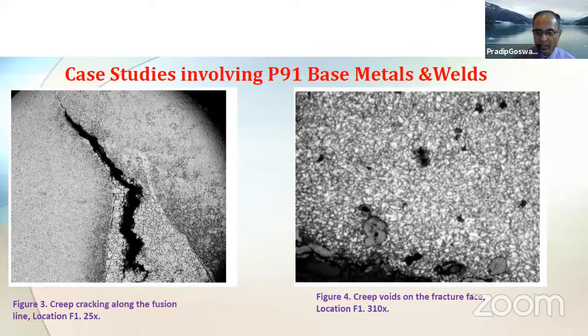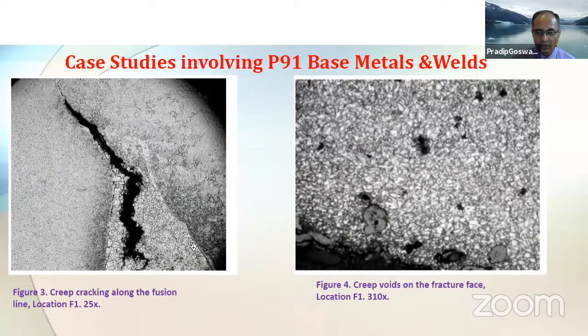And these were the typical creep voids or the creep deformations noted around the welded and fusion lines. These are the typical creep micro voids. That means, assume this is like a creep crack. This will not happen abruptly. It doesn't happen overnight. Creep failure happens over the years. And typically over a period of time, when all these micro voids are created by this high temperature deformation, they tend to join up and then lead to this form of creep crack.